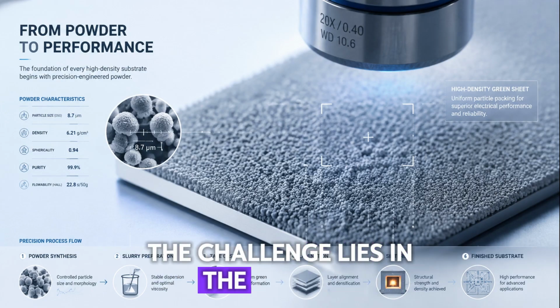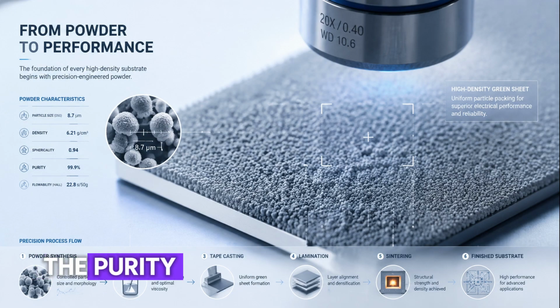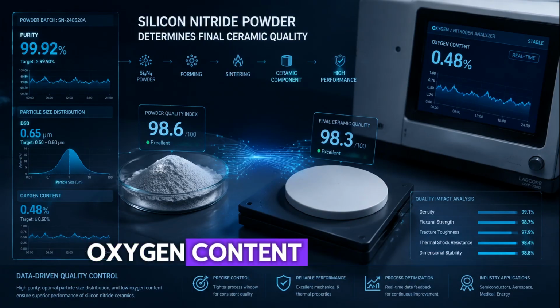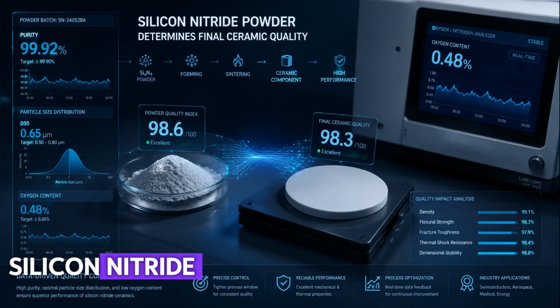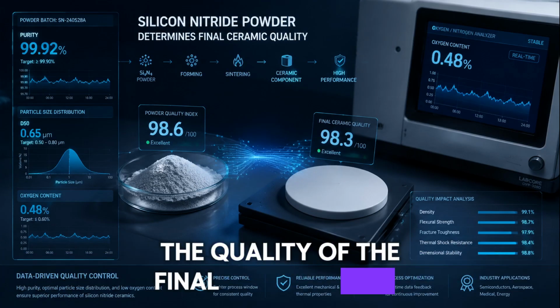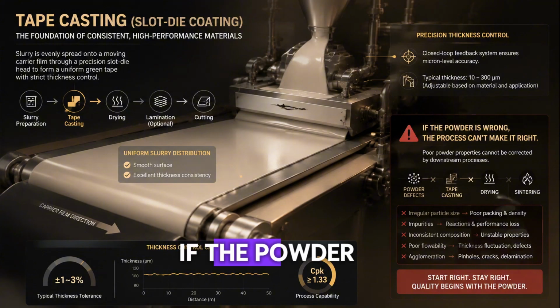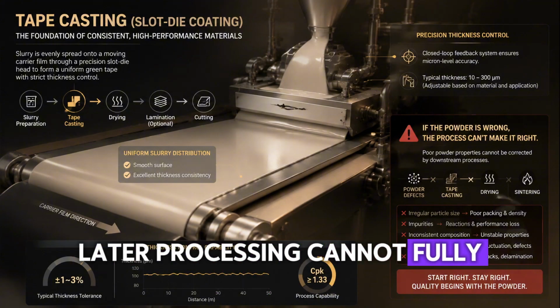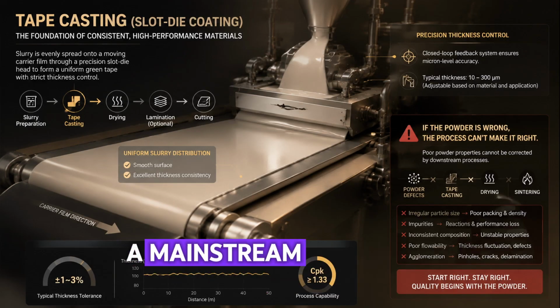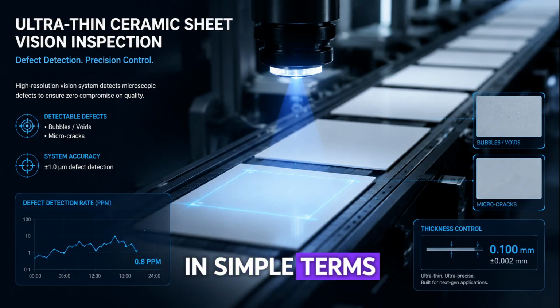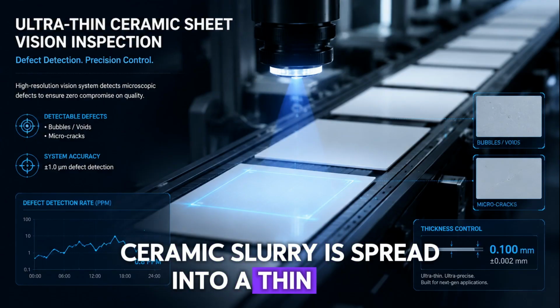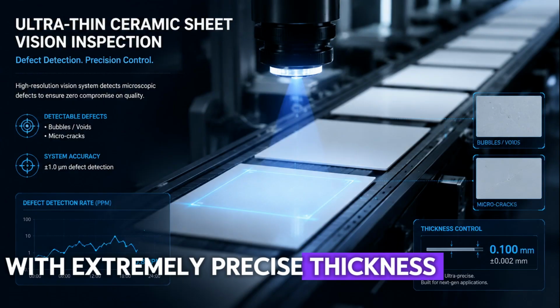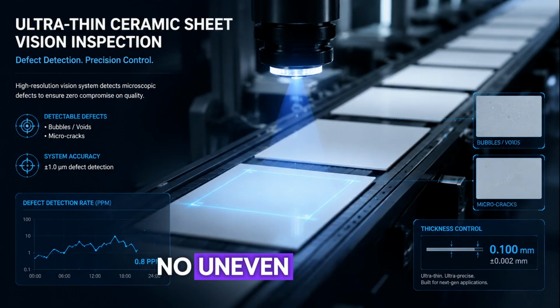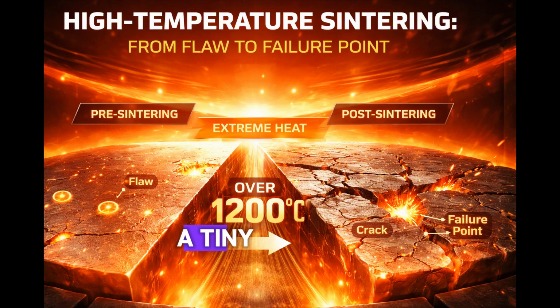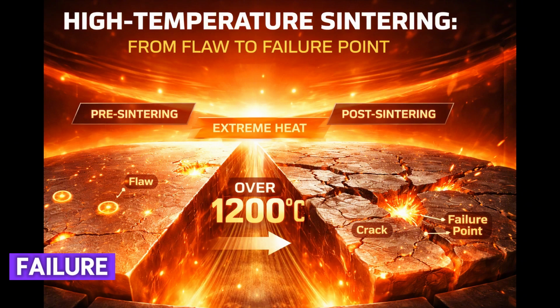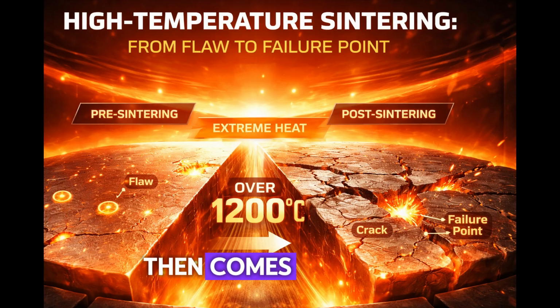The challenge lies in the process. It begins with powder. The purity, particle size distribution, oxygen content, and impurity control of silicon nitride powder directly determine the quality of the final ceramic sheet. If the powder is not right, later processing cannot fully fix the problem. Then comes forming. A mainstream method is tape casting. In simple terms, ceramic slurry is spread into a thin sheet with extremely precise thickness control. There can be no bubbles, no uneven settling, no hidden microcracks. A tiny defect at this stage can become a major failure after high-temperature sintering.